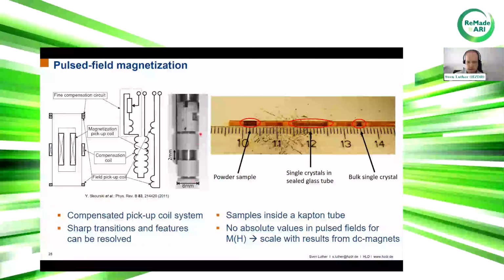For this pulse field magnetization, the preparation is done by putting your samples in such a Kapton tube. You can see I was able to measure different types of samples. For example, a powdered sample, which is fixed with some wooden plugs inside these Kapton tubes. I was also able to measure highly air-sensitive single crystals in a sealed glass tube, which you can see here. But I was also able to measure a bulk single crystal. But I have to say, in these magnetization measurements we are not able to measure absolute values in the pulse field. So if you measure magnetization in pulse fields, you always have to scale your results from DC, so from static magnets.